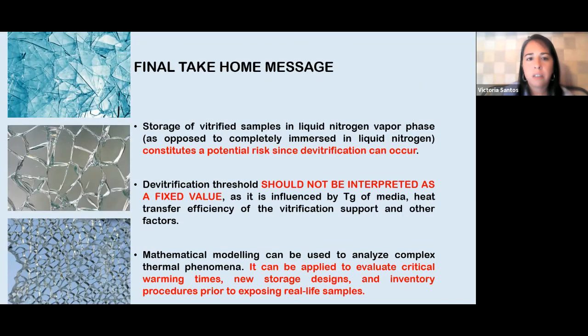Final remarks. Storage of vitrified samples in liquid nitrogen vapor phase constitutes a potential risk since devitrification can occur if we disturb these nitrogen vapor layers. Devitrification thresholds should not be interpreted as a fixed value since they are influenced by the TG of the media and the heat transfer efficiency of the vitrification support, because it's not the same if we have a cryotop or an OPS or a cryoleaf or any other vitrification device that has different loaded volume in it or different thickness in the plastic supports.